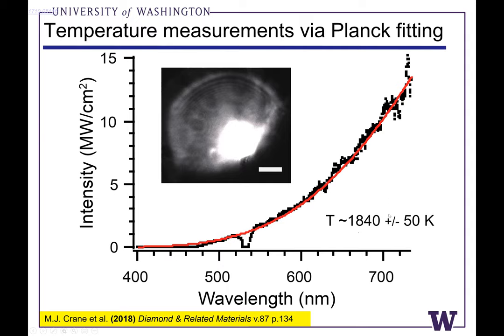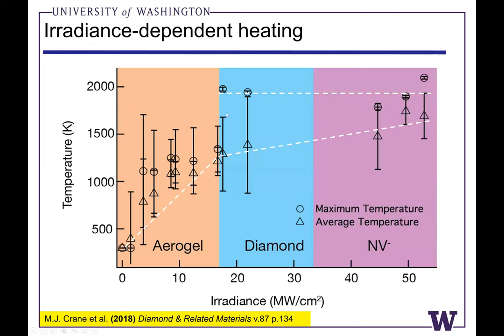And there are certain moments where we see these very bright flashes. They're difficult for us to capture in time. They're sort of spontaneous. We see these little pops of white hot emission. And if we fit these as we increase the laser power and just collect these Planck spectra progressively, we see these really sharp and rapid bursts of temperature for very brief moments of time.